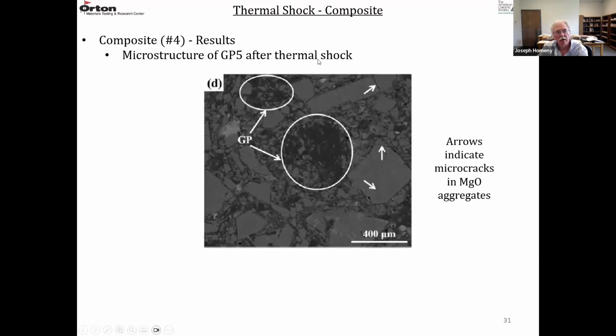And then this is GP5 after thermal shock. The arrows are again showing the microcracks that are present, but the density is really decreased. So there's some damage in the coarser aggregates, and then there's microcracking in these pellets. So this is probably one of the reasons why the strength goes up after thermal shocking: because of the less damage in the coarser aggregates.